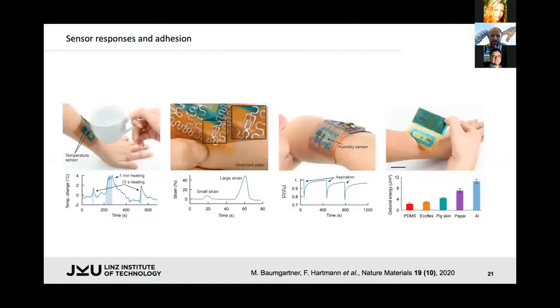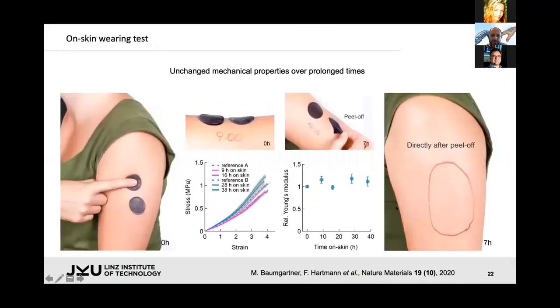Actually, to summarize this, we put a little bit of effort in this to test how biocompatible gelatin actually is. And we wore it, so the students wore it on the hand, and they peeled it on and off again. And we found that the skin doesn't get irritated at all, even if you wear it for more than 40 hours. Eventually that has to be extended, but still, this is how far we went for this paper. But more importantly, also the material itself doesn't degrade when you wear it on the skin. So even though you do sports, you sweat, even though it's a hydrogel, the mechanical properties actually remain intact for a certain amount of time. So this is also something that we're looking into.